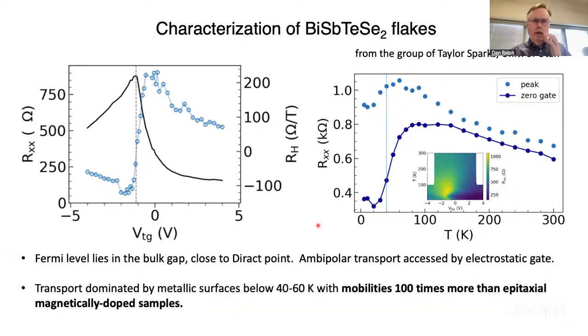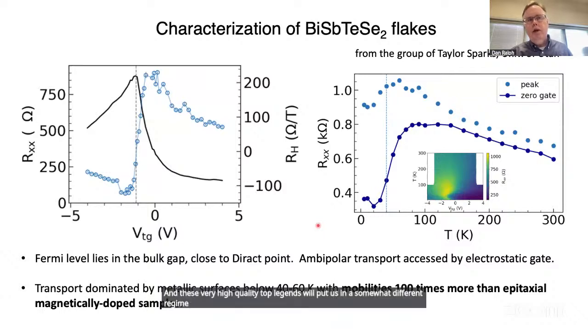And these very high quality topological insulators will put us in a somewhat different regime than what's been done previously with the magnetically doped topological insulators, in that we have mobilities about 100 times more than the epitaxial magnetically doped samples, with the topological insulators by themselves. And even once we add the magnets, we're seeing mobilities 10 times what's been measured before with the magnetically doped topological insulators.